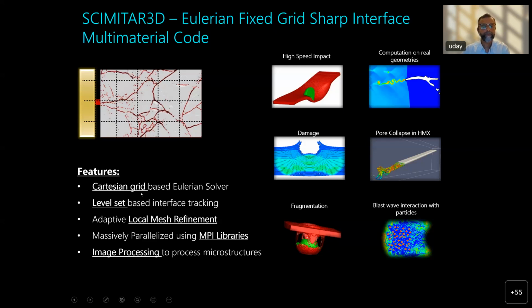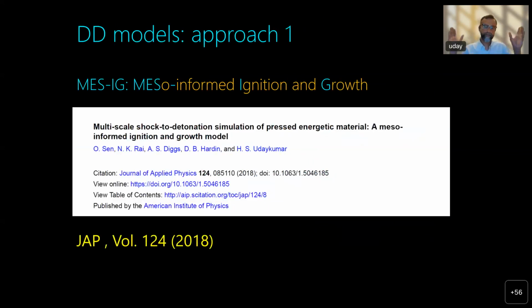It is a fixed Cartesian grid Eulerian sharp interface solver, which means that all the interfaces you see here between materials are treated sharply and tracked very much similar to front tracking, but using level sets. So it's a level set based technique. What you see here, for example, are zero level sets of the plate and an impactor. And so we track explicitly the level sets. It's got adaptive local refinement to get features that are very fine. And it's parallelized and uses image processing to process microstructures. So we can go directly from an image to a full-blown calculation on a fixed mesh using Scimitar 3D. Everything on the mesh is described in the form of level sets. Okay, so that's the solver, and we're going to use that. I'm not going to talk about the solver anymore because that's what we're going to use for all our simulations.